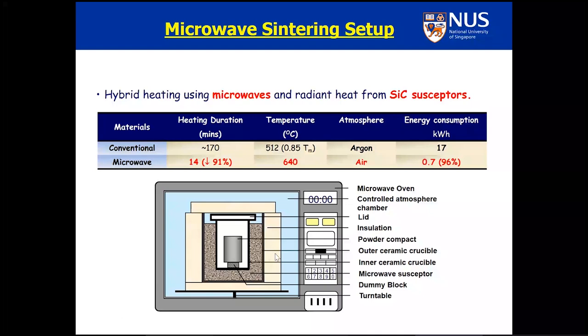Now, you can pre-calibrate this: 1 minute, 100 degrees centigrade, 2 minutes, maybe 180 degrees centigrade. So you know exactly, if you want to reach 640, for example, in our case, we need 14 minutes. It's very simple. Once you switch on the microwave, it heats the susceptor and also the billet from inside out, and the susceptor heats from outside to inside. So there's a two-way heat front which helps you reduce the heating or sintering time by 90% and the energy levels also by 90%.